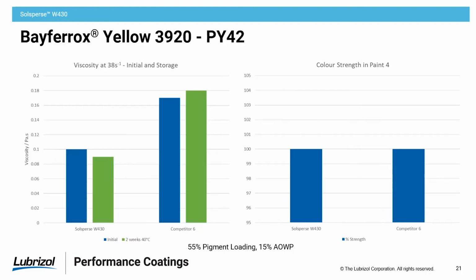Right. Yellow iron oxide can be a challenge. This is a 55% grind at the 15% additive on weighted pigment. You may remember that with the red iron oxide, which is a larger particle size, we had 60% loading, but 1.25 additive on weighted pigment. So we're almost 10 times or more than 10 times higher in the dispersant demand to adequately disperse the yellow iron oxide. So yellow iron oxide can be a sort of a distinguishing pigment when we're looking for dispersant performance.